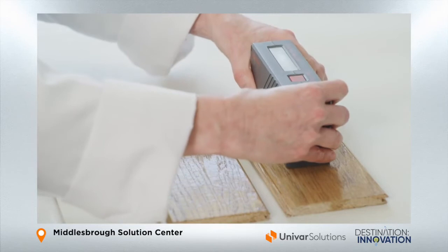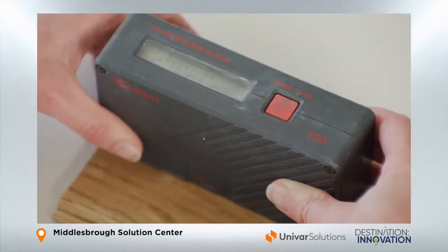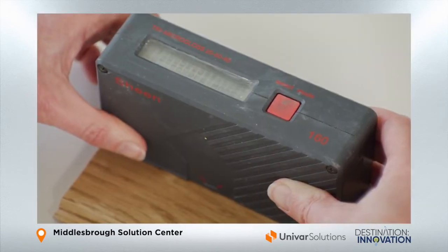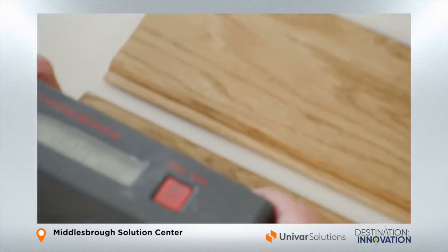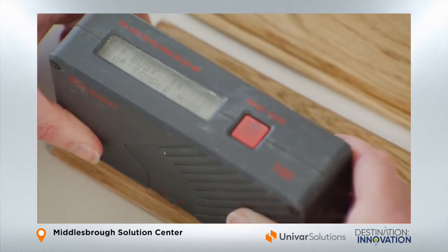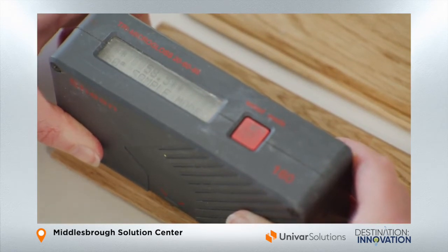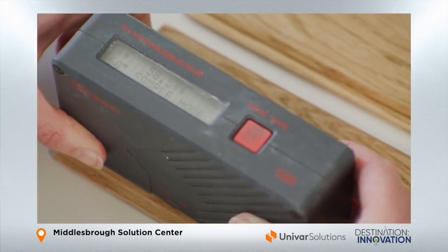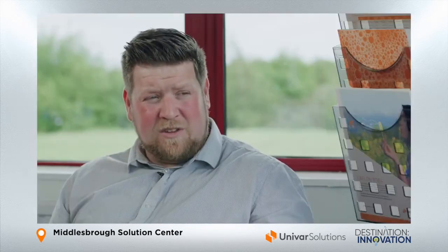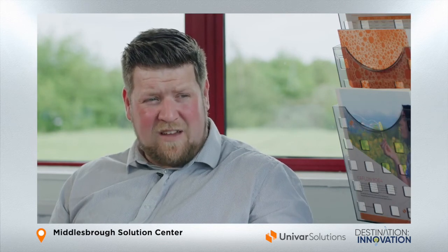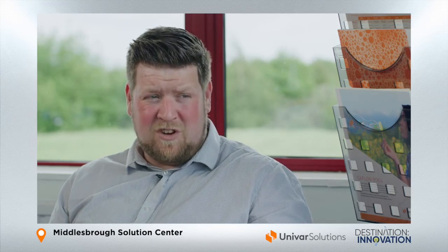But interestingly, we measured the gloss of both the coatings as well, and even with the silicone additive, the gloss really wasn't reduced. So one with the additive, and the value is still quite high at 57.3. And then without the additive, you can see that it's just a very small difference when we've measured the gloss at 60 degrees. We also now have a colorimeter, so we are able to measure colour in the LAB scale. The L value is how black or white the material is, the A value is how red or green the material is, and the B value is how yellow or blue the material is.